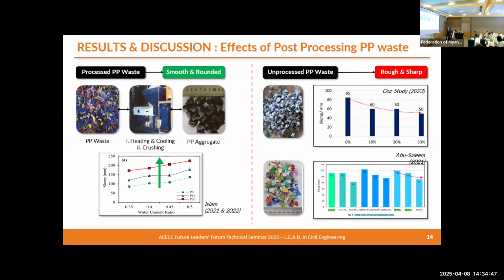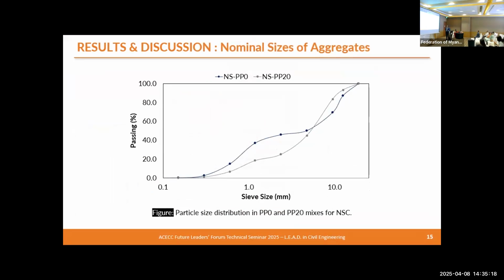In the post-processed case, the plastic waste is the same size as the natural coarse aggregate, and the surfaces are smooth and rounded. But in our case, there was a mismatch between the nominal sizes, and on the other hand they were rough and sharp. So due to these reasons, when the plastic waste is post-processed, we can increase the workability with this incorporation, but when it's not post-processed, we can't. There's a workability reduction that we should keep in mind.